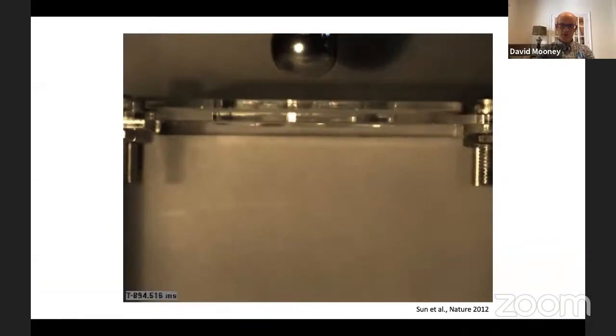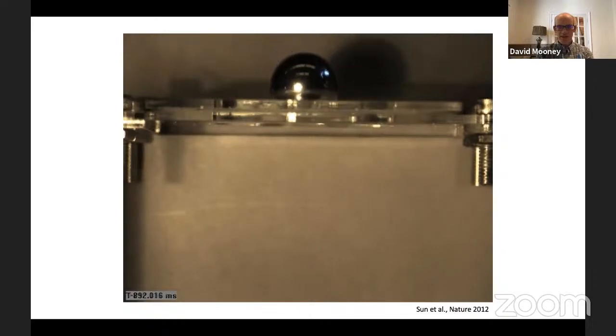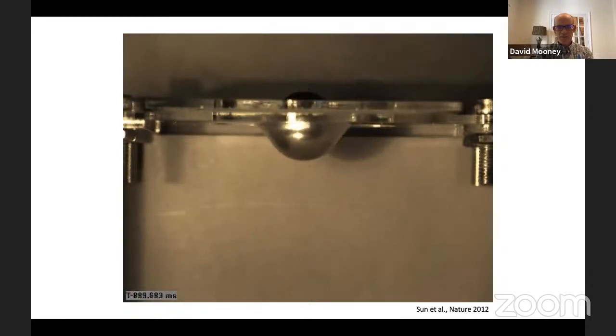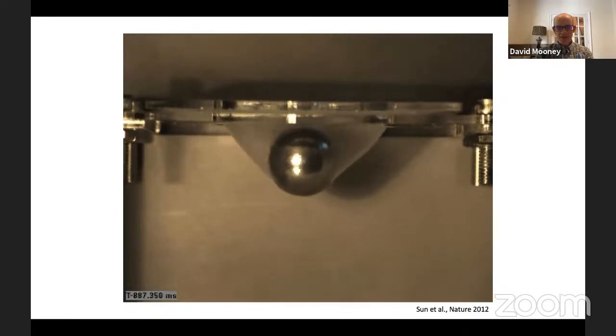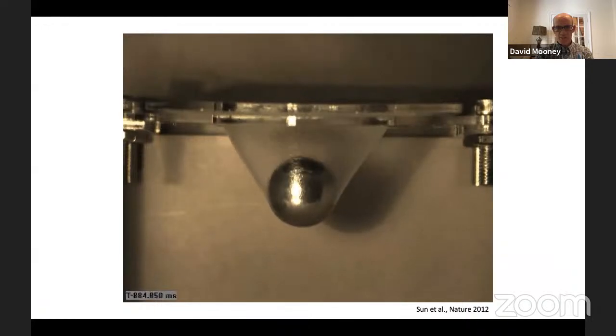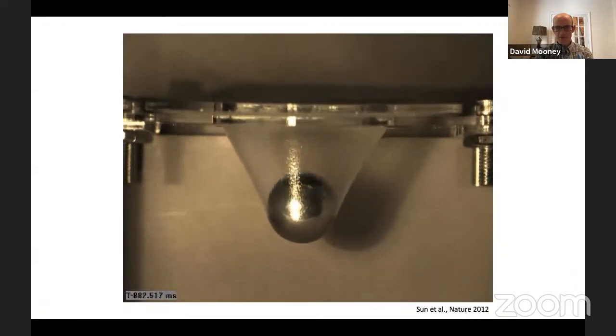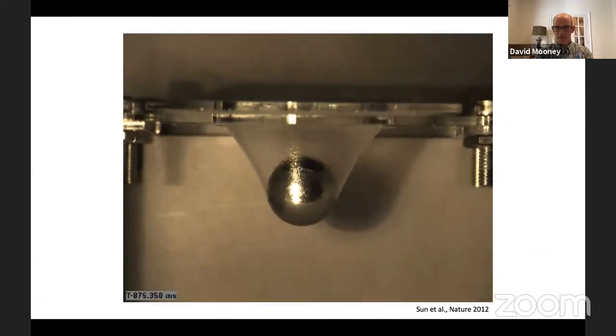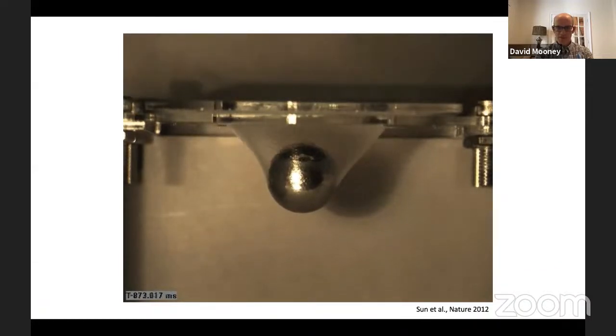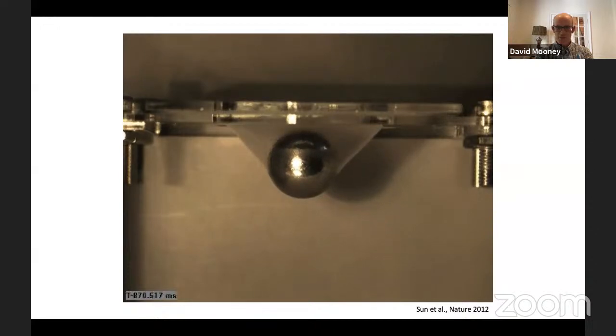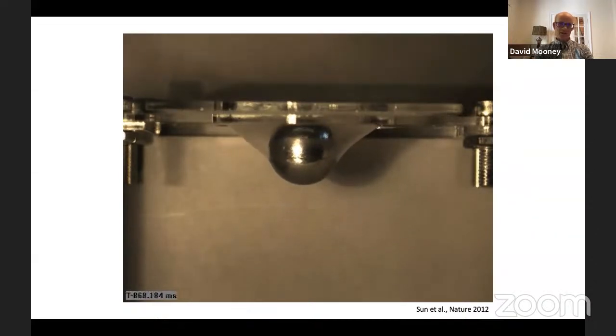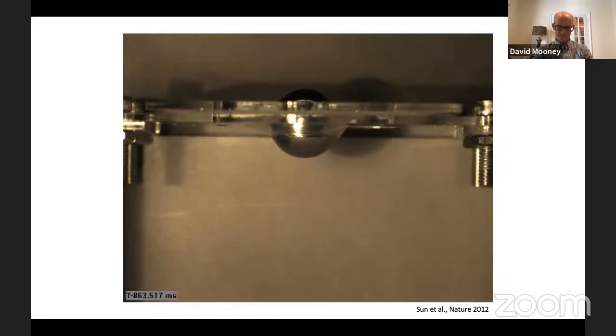They were able to demonstrate this idea pretty spectacularly. And here's a nice video demonstrating the idea, where this is a 1-inch steel ball that was dropped from 6 feet onto a 1 millimeter thick layer of hydrogel. You can appreciate that the gel not only doesn't break, but it actually is able to return a lot of the energy back to that ball and will send it flying back up again, although it will have dissipated quite a bit of the stress.